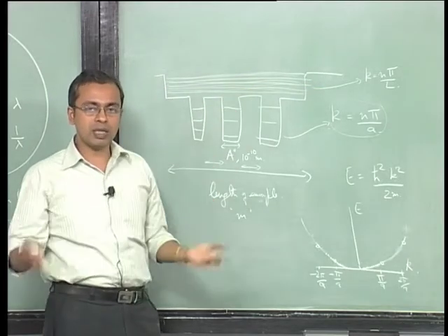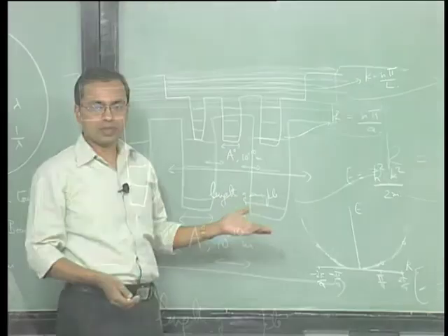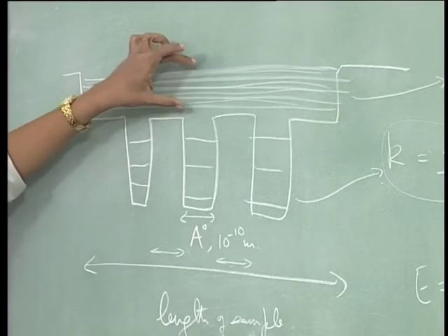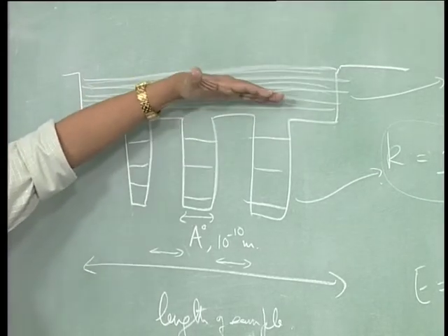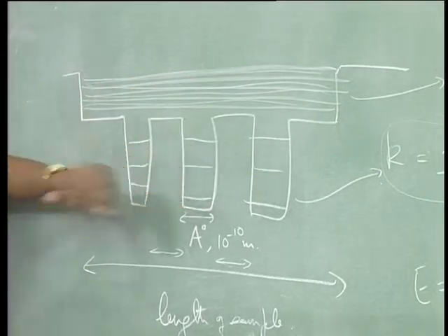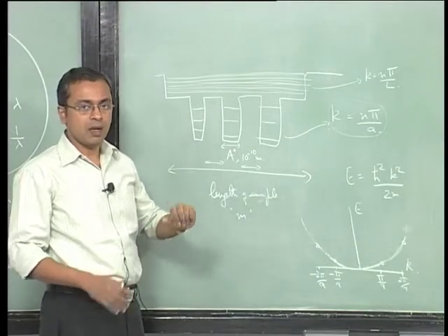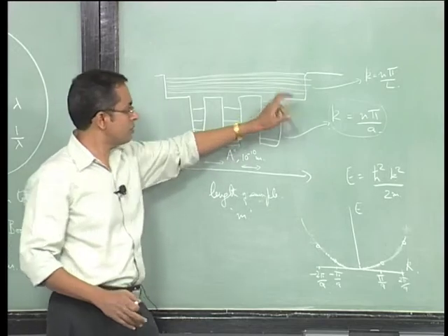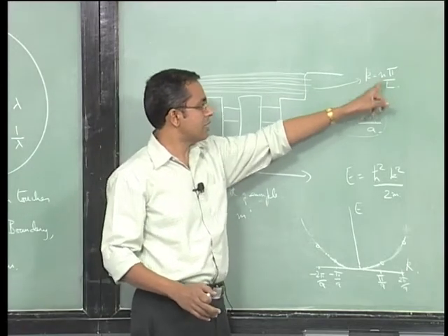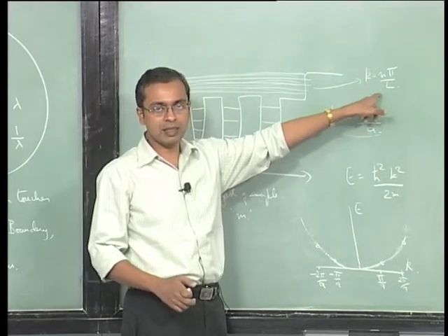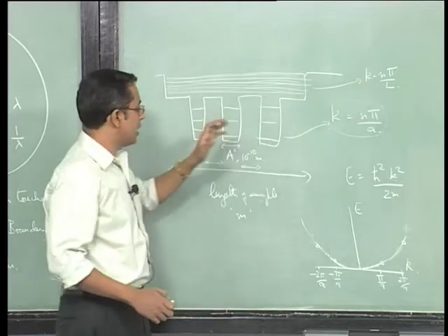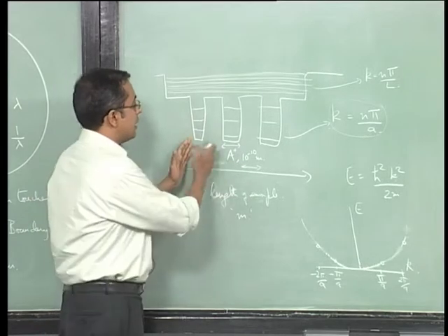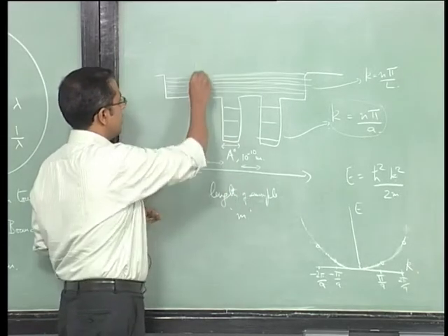The issue that we had not accounted for so far was that we never bothered about the structure. When we simply said the number of free electrons per unit volume, we treated these nearly free electrons as though they were not affected by the presence of this periodic structure. What we now recognize is there is a wave vector associated with these nearly free electrons, and the allowed wave vectors are given by this information here. Those allowed wave vectors can and will interact with the periodic structure that is defined by these locations.